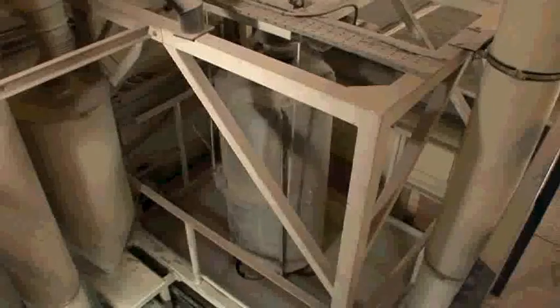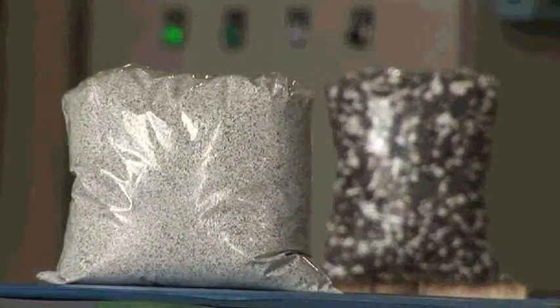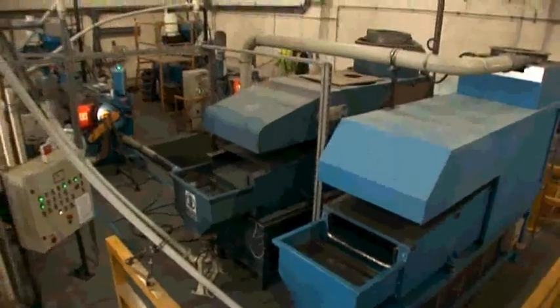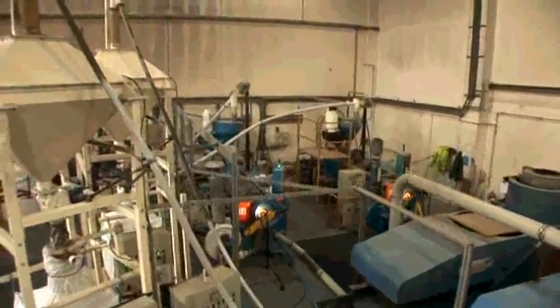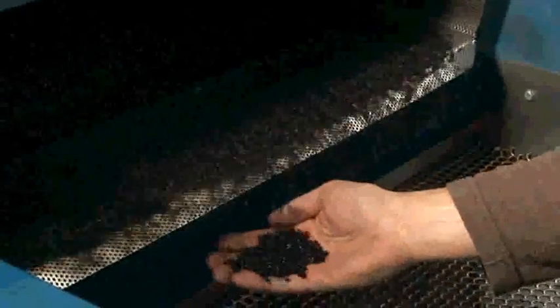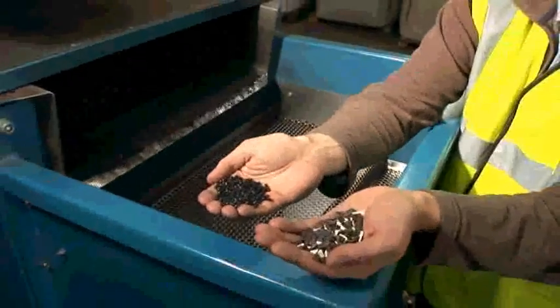One option is to grind the granulate down into a powder. This is sieved to control the particle size for uniform powder density, ideal for high-volume extrusion. Alternatively, we have developed a pelletizing process which allows the granulate to be filtered as a melt to remove the finest of contamination that may be left. The resulting pellet is both clean and extrusion friendly.